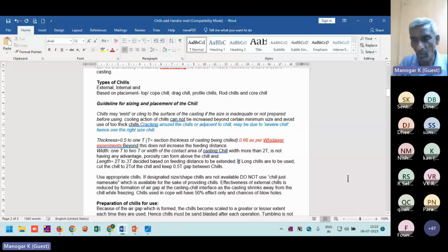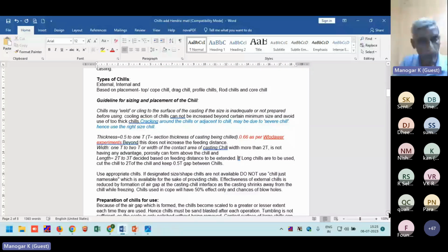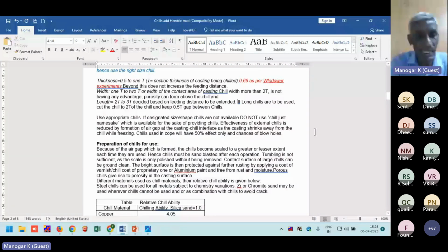People use up to half of the profile also. And the use of chills is important. Prepare the chills properly, grind, coat with a seal coat, and use a correct chill based on the section thickness and the type of chill given in the method card. Do not use the chill just for namesake, because we always see some people make wrong chills that fuse with the casting or cause problems in bulk castings. So chill management is important in the foundries.